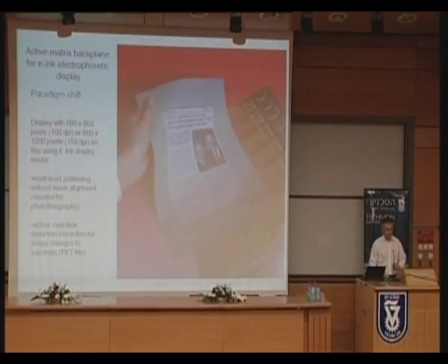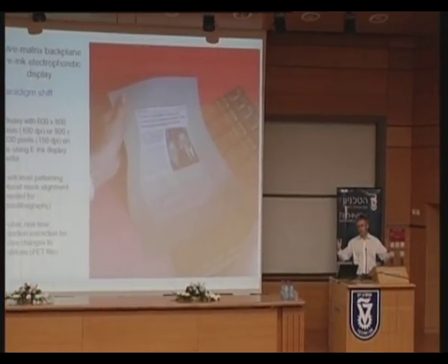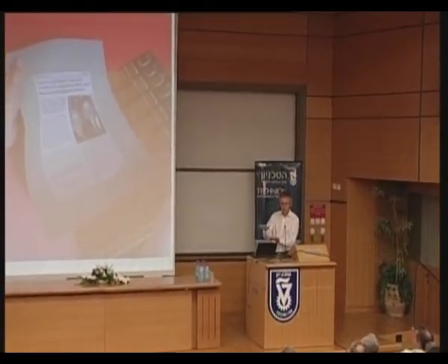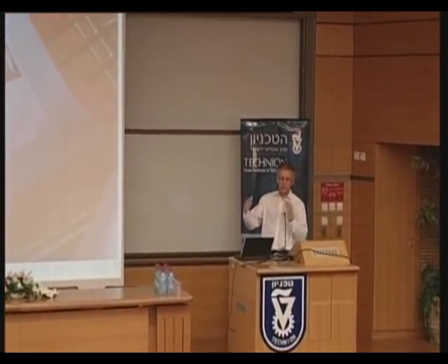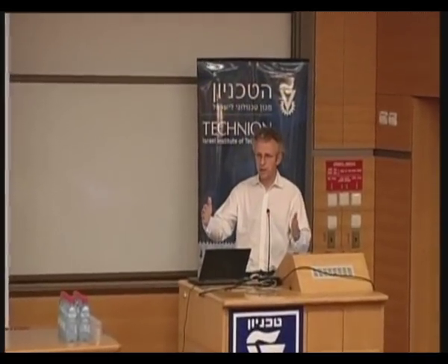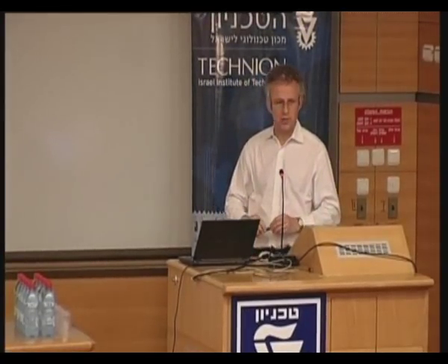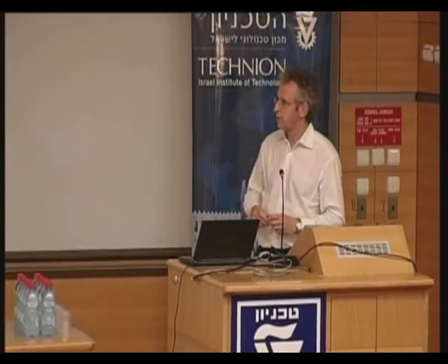Now, it turns out the biggest challenge in this is that we can't use mask alignment. We have to use innovative patterning techniques for the higher-level patterning steps because the substrate itself is not sufficiently geometrically defined or rigid that a mask would line up from one mask process to the next. The distortion of a fraction of a micron over a length of tens of centimeters is very hard to avoid in a sheet of plastic, particularly if you've had to cycle it in temperature, as you would have had to if you'd used silicon as the semiconductor. So what has been done here is to use patterning techniques such as inkjet printing, where it's possible to do on-the-fly correction in real time so that the printing of higher-level metallization, say, is done in registration with the lower-lying pattern, even in the presence of mechanical distortion.